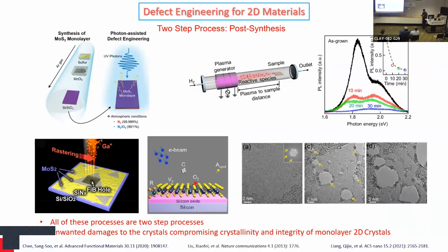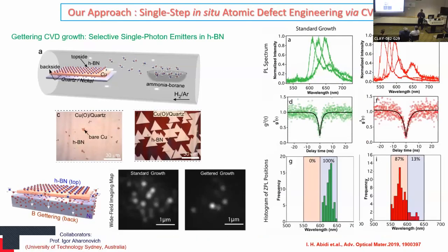Normally, whatever defect formation techniques are available for these monolayer 2D materials are mostly two-step. We need to do this in the post-synthesis part. First we have the material, and then we do the defect formation, maybe through ion implantation or through electron beam irradiation. So we can use these kinds of two-step processes to create some defects in the material. But these techniques are not very controllable. You can create even some voids within the material, or maybe the material breaks or something. So it's not what you would want for very controlled atomic defects. This can be done with CVD itself as well. So I use CVD again as a tool to create some defects in the materials.